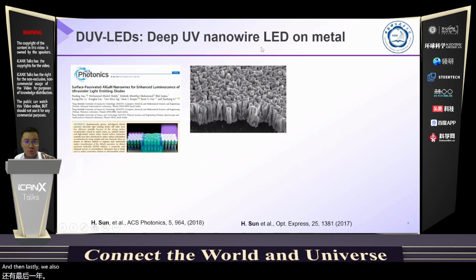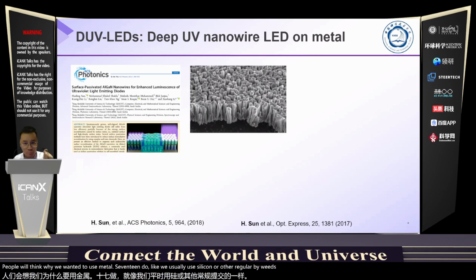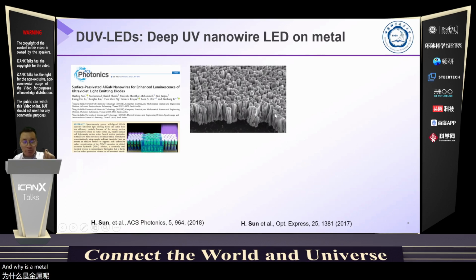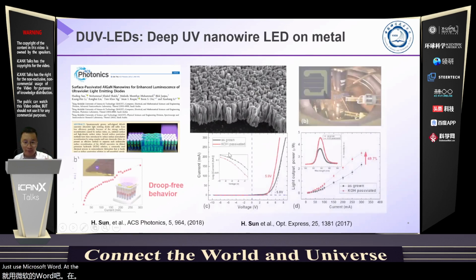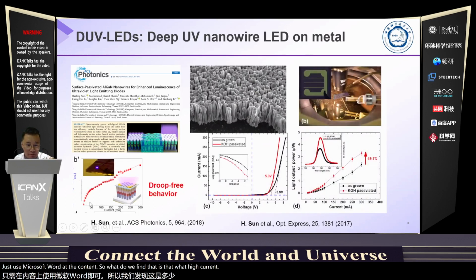And lastly, we also use nanowire LEDs on metal. People will wonder why we want to use a metal substrate, right? We usually use silicon or other regular substrates, but we propose to grow nanowires on metal. Metal has a very good heat dissipation channel, and metal can be used directly as a contact. You don't need to make more contacts, you just use the metal substrate as a contact. What we found is that at high current injection, more light can be generated. And surprisingly, at high current injection, the efficiency doesn't drop. Basically, we demonstrate droop-free behavior of the nanowires grown on metal, because metal has very unique features, as I said: a high heat dissipation channel and directly making the contact.